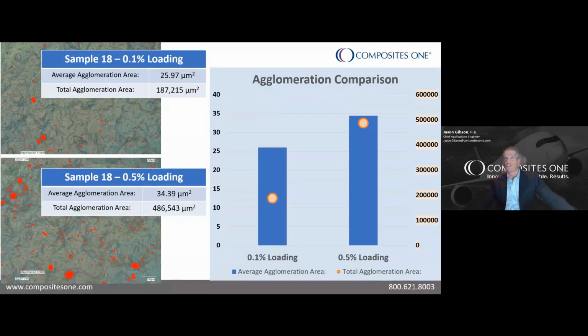Now, we also want to try to understand why the 0.5% loading did not perform as well as the 0.1% loading. So to do this, we looked at sample 18 at both loading levels under a microscope. On this slide, I'm showing the 0.1% loaded sample on the top left and the 0.5% loaded sample on the bottom left there. By polarizing the image, the graphene is highlighted, and we can calculate the size of graphene agglomerations in both samples. Now, these agglomerations are where the graphene clumped together and did not fully disperse into the solution. You can see these clumps, or agglomerations, on the two images on the left. I've highlighted them in red.